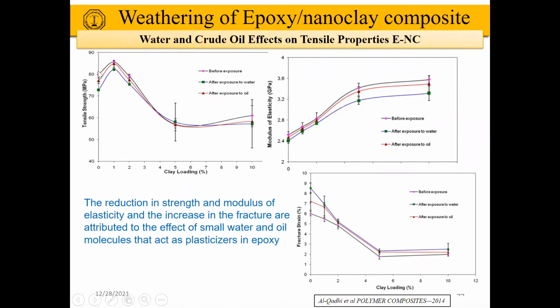And how does that affect the tensile strength and the modulus of elasticity? We looked at the tensile strength. You can see before and after 1%, well, this is the same result as we have seen. But what if we expose it to water? You can see that if we expose it to water, you see the blue line here, there is also an increase in strength due to the presence of 1% clay.